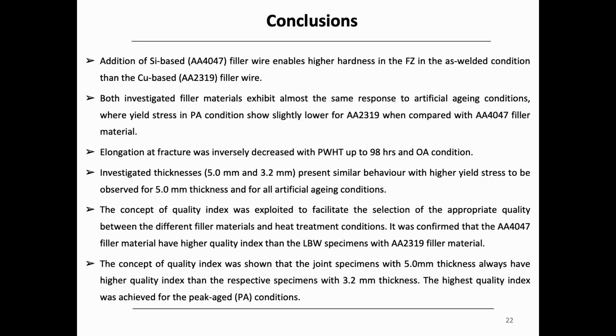And the concept of quality index was exploited to characterize, to assess and to quantify the mechanical performance of the welds. It was shown that the joint specimens with a thickness of 5 millimeter always have a higher quality index than the respective specimens with 3.2 millimeter thickness. The highest quality index was achieved for the peak aged conditions. Yeah, thank you very much for your attention.